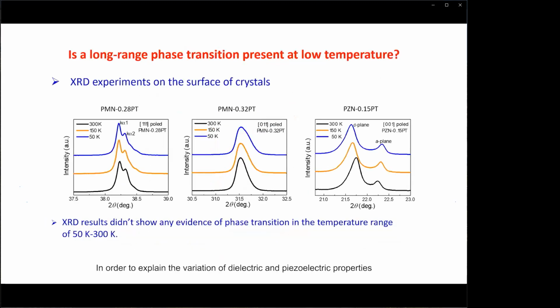In order to explain the variation of dielectric and piezoelectric properties at cryogenic temperatures, firstly, we checked if there is any phase transition in the temperature range. As shown here, XRD results didn't show any evidence of phase transition in the temperature range from 50 to 300 Kelvin for all these crystals: rhombohedral, orthorhombic, and tetragonal crystals.